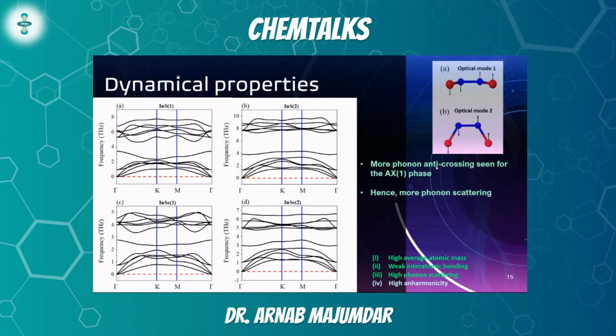Okay, now, the dynamical properties or the phonons. So if you remember, the third criterion of Slack, which I've written on the bottom right corner again, was that we needed high phonon scattering. Here, I have just shown the same thing for two particular materials. I could have shown it for all of them, but this paper had a lot of graphs. So here I've just shown it for indium sulfide and indium selenide.